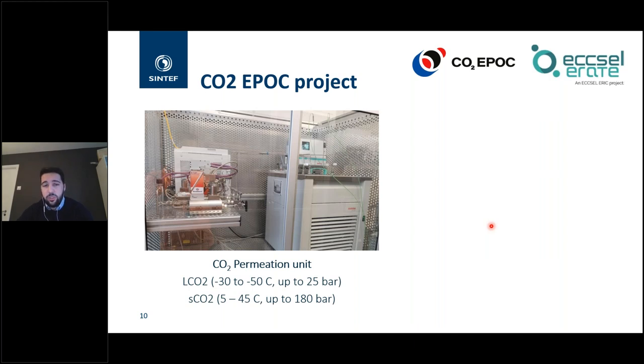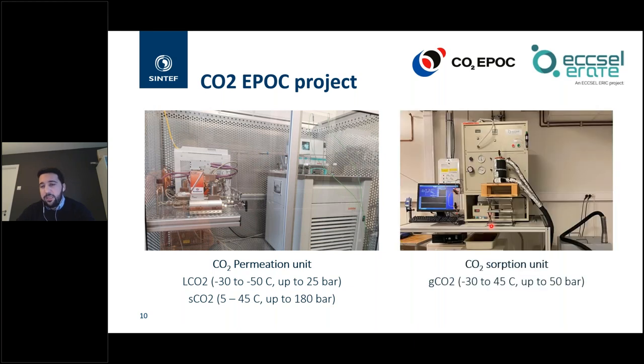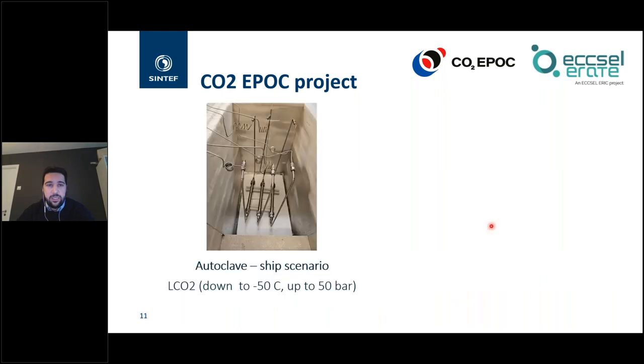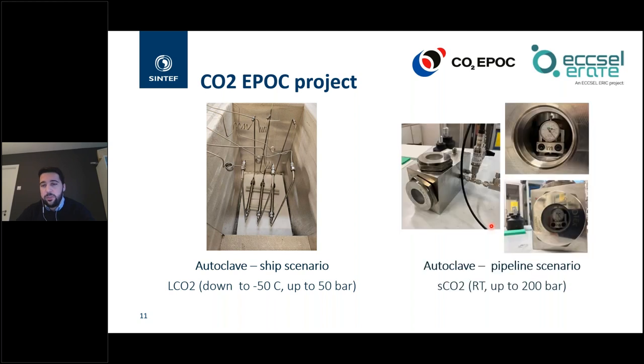In the project we established infrastructure: a CO2 permeation unit working with liquid or supercritical CO2 to determine barrier properties of polymeric materials; a modified CO2 sorption unit to better understand kinetics and thermodynamics of CO2 sorption, useful for developing models; and autoclaves for the ship-based scenario with liquid CO2 and for the pipeline scenario with supercritical CO2.